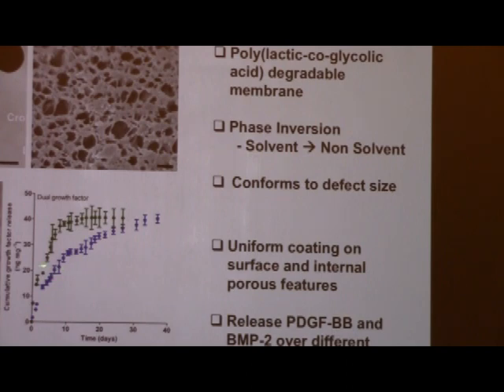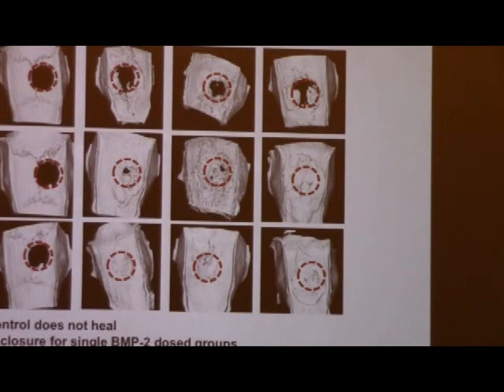And he gets a release profile that looks like this. Here you can see the time in days, and here you can see the cumulative amount that has come out of the film. And you can see that all of the PDGF is out in about a week. And we're getting a very nice, for us, low dosage of nanograms per milligram. You can see the BMP2 comes out in a period of somewhere between 3 and 4 weeks. And so it's much slower. And this is the kind of staggering that we like to have in this system.